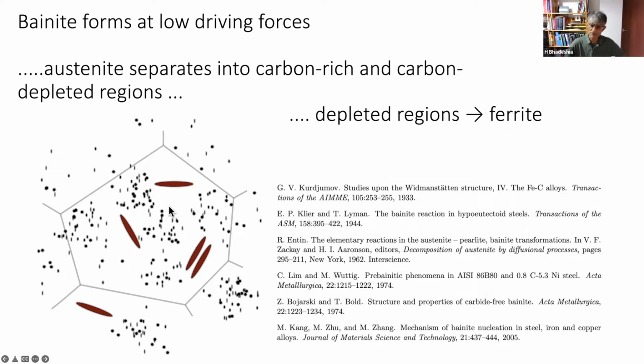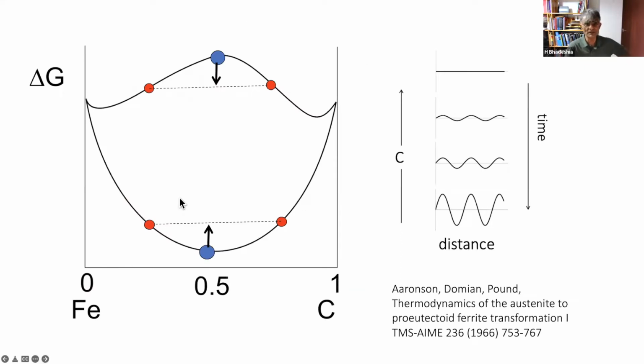So the only way you can get carbon-rich and carbon-poor regions is by a process called spinodal decomposition, and that's illustrated over here. If your solution has a free energy curve like this, then any perturbation of composition will lead to an increase in free energy. So that's not possible, okay? But if your free energy curve is like this, that means carbon atoms prefer to be next to carbon atoms and iron atoms next to iron atoms, then a perturbation becomes stable.